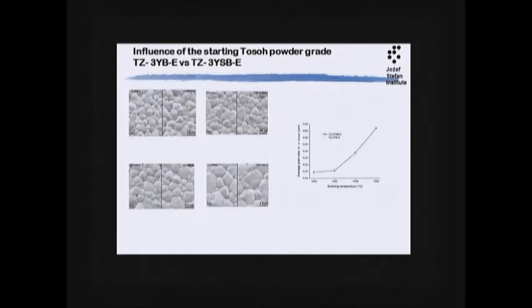And we did the work, we took both materials, and we pressed them into pellets, and then we sintered them at 1400, 1450, 1500, and 1550 degrees. And you can clearly see that there is no difference in the grain size. And when we also measured that, we confirmed there is no difference. You can take either of these two materials, and if you sinter it at that temperature, there won't be a big difference, okay? Sometimes it was confusing what was done with what.